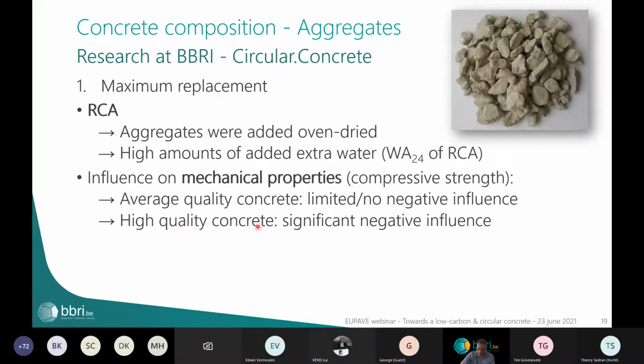And we saw that in fact, when we look at the average quality concrete, the use of these aggregates in very high percentages did not lead to an important negative influence after 28 days. After 91 days, the influence became much more clear, but after 28 days, and this is still the time during which the evaluations are made for the most part, there was no or very limited negative influence.